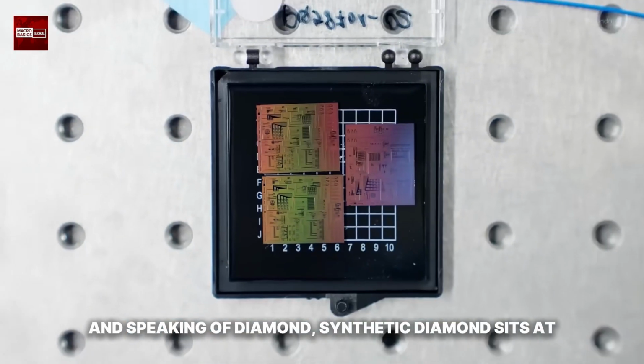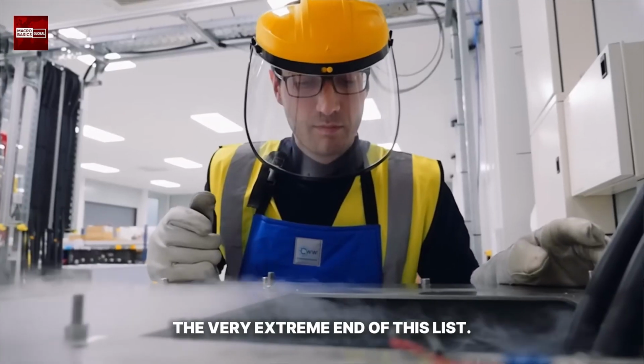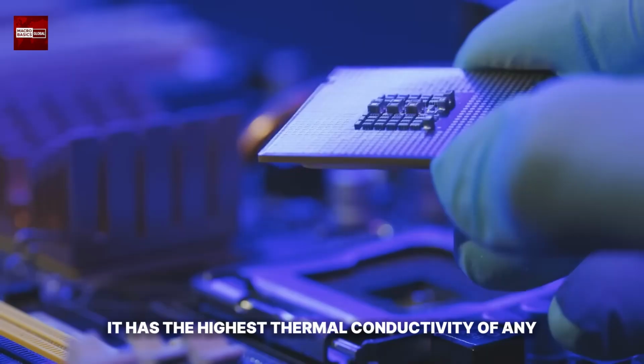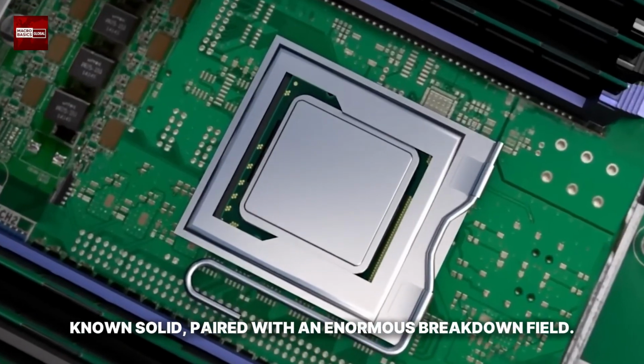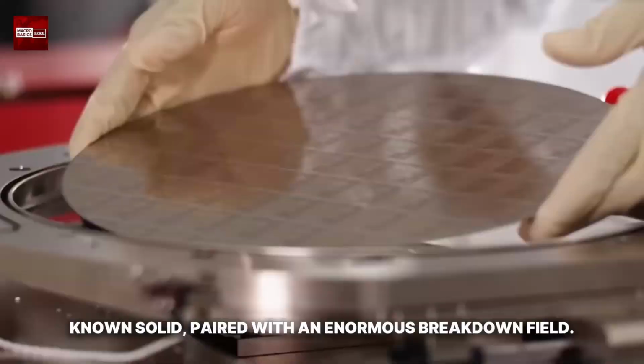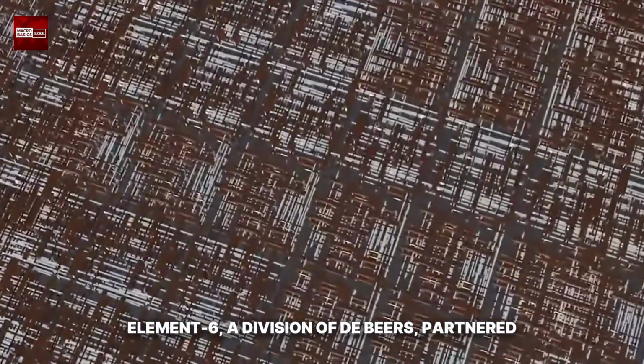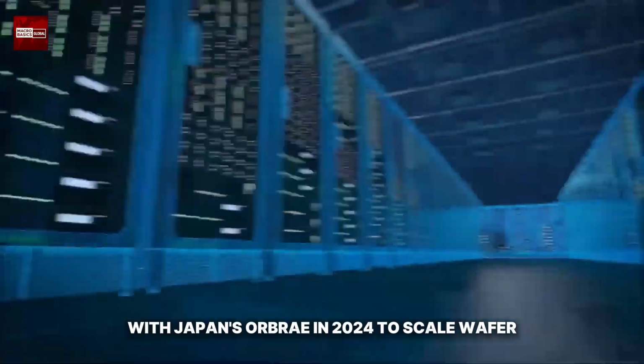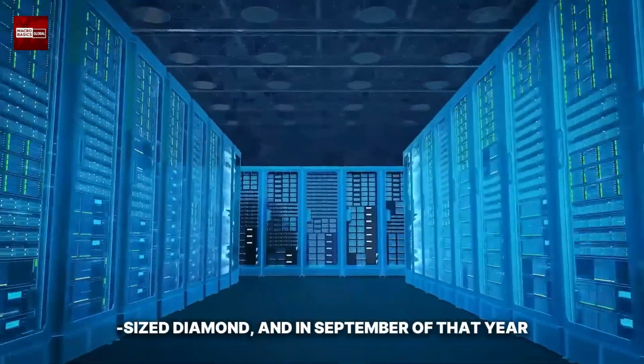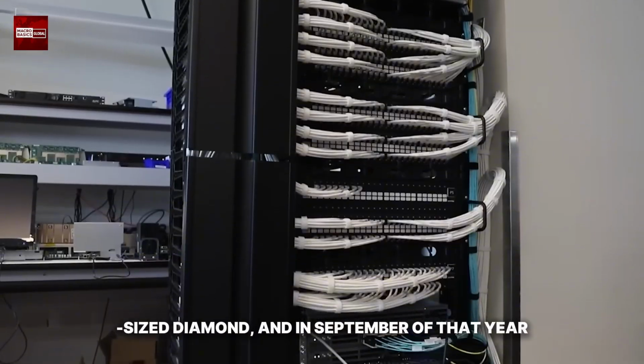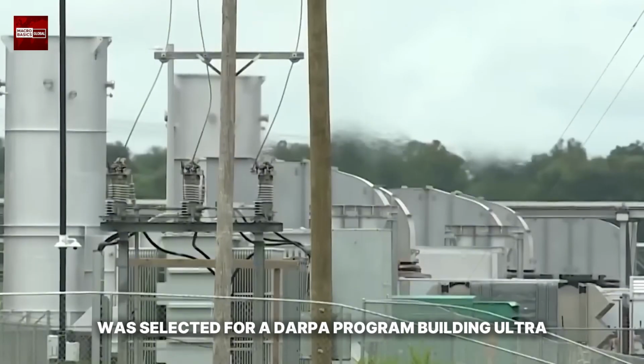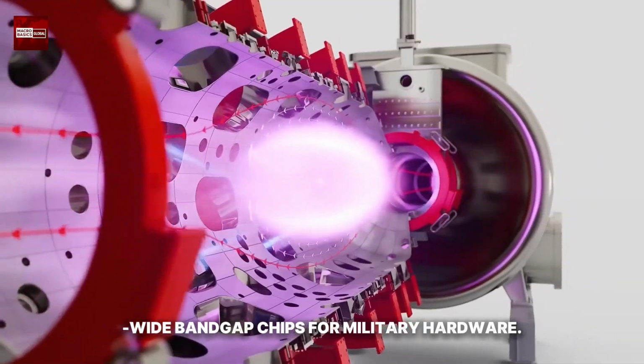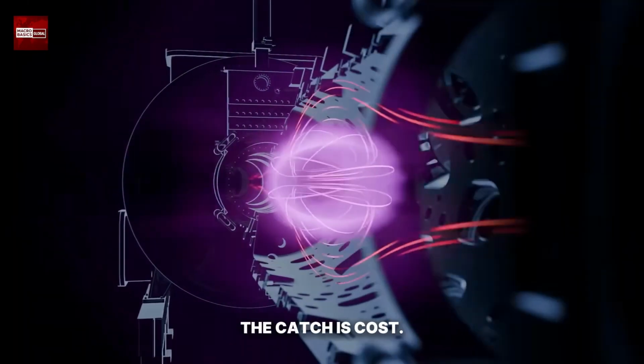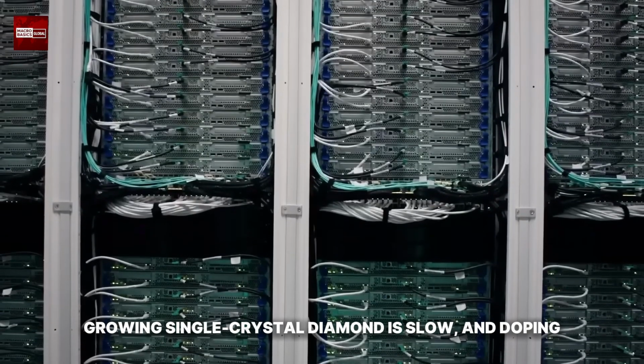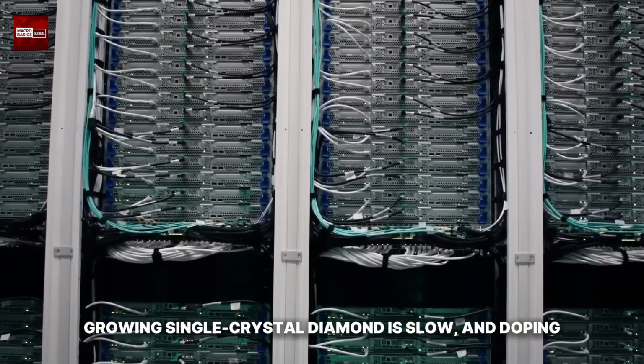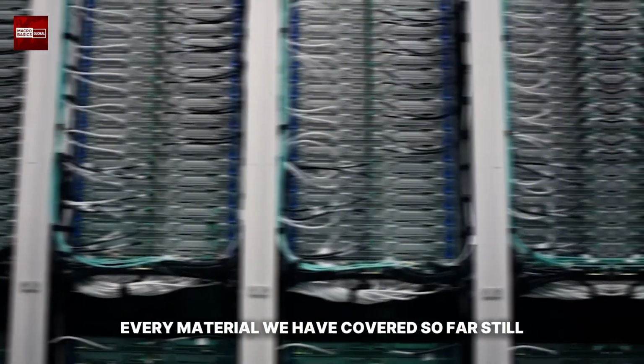And speaking of diamond, synthetic diamond sits at the very extreme end of this list. It has the highest thermal conductivity of any known solid, paired with an enormous breakdown field. Element Six, a division of De Beers, partnered with Japan's Orbray in 2024 to scale wafer-sized diamond, and in September of that year was selected for a DARPA program building ultra-wide bandgap chips for military hardware. The catch is cost. Growing single-crystal diamond is slow, and doping it remains genuinely difficult.